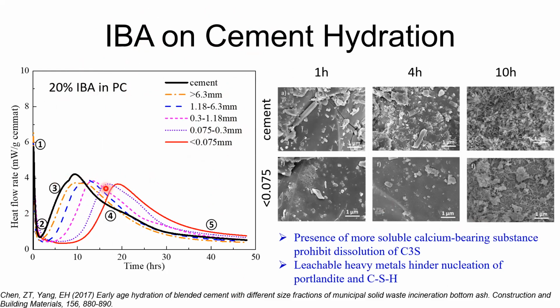Under SEM, we can observe this on pure cement after 1 hour and up to 10 hours of hydration - you'll see the hydration product formation on the surface of the cement particles. However, when the smaller particle size of IBA is used, you find a very clear delay in the formation of hydration product.